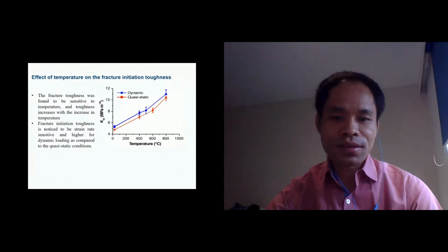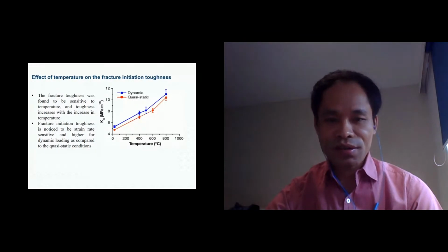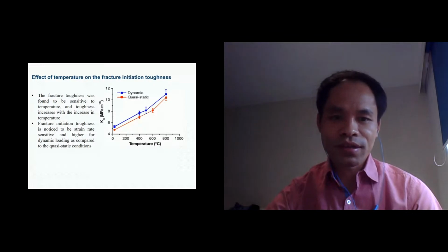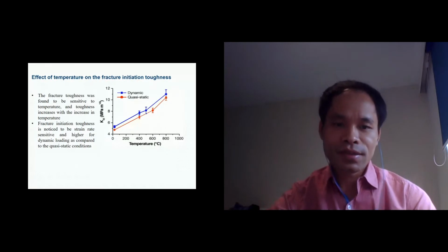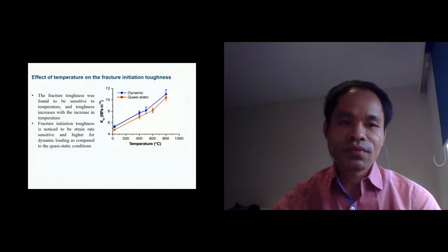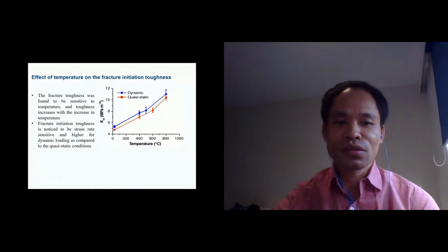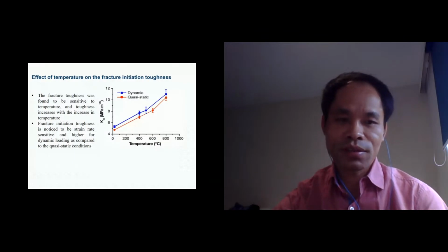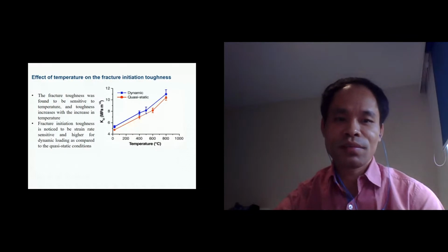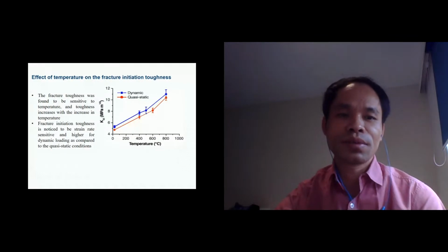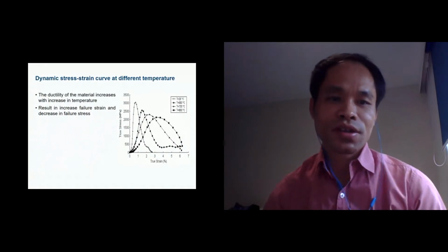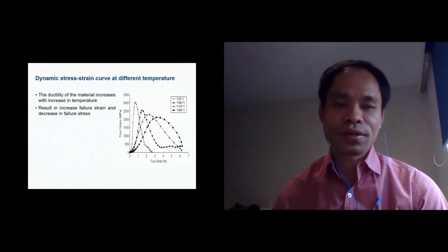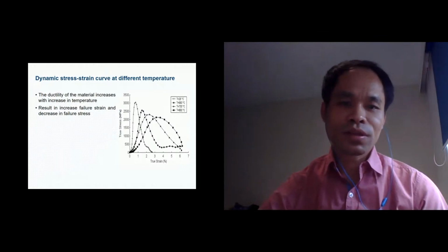In this graph, it says that when the temperature increases, the initial fracture initiation toughness increases. This is more evident for dynamic loading than quasi-static. However, this research also mentions that fracture initiation toughness is noticed to be strain rate sensitive. So, some other people are also researching stress-strain curves at different temperatures to see how they vary.